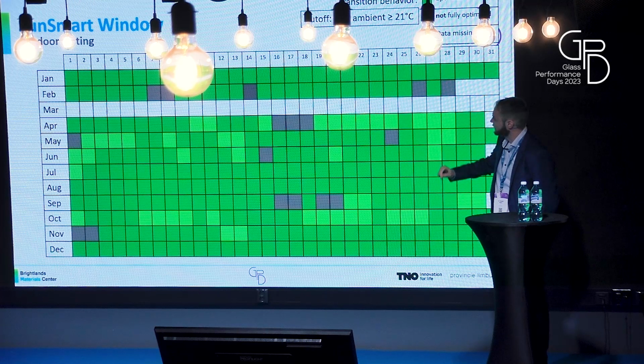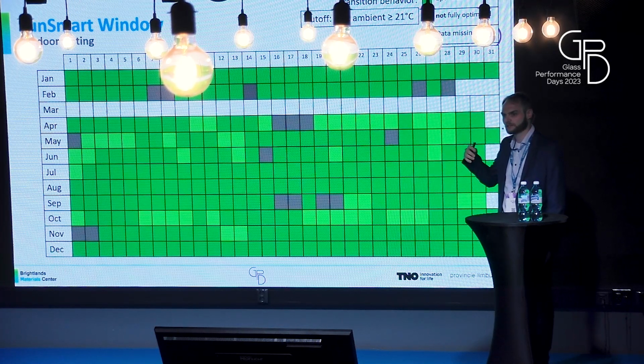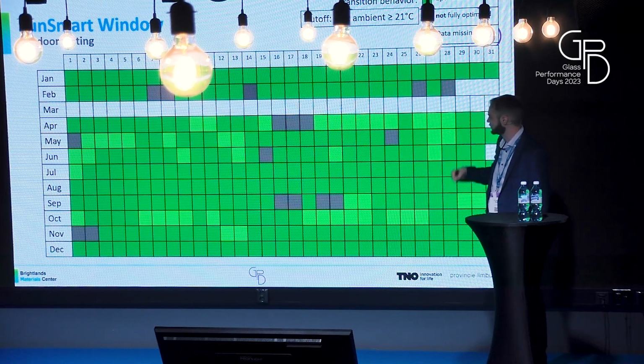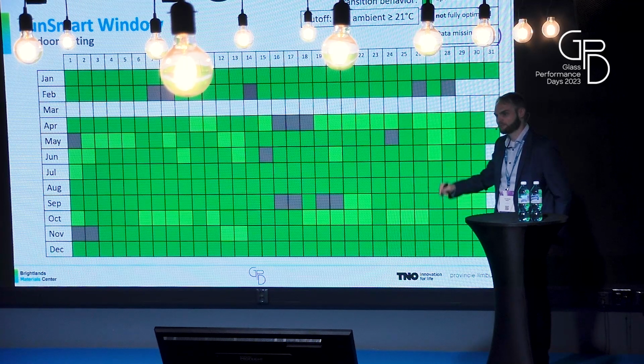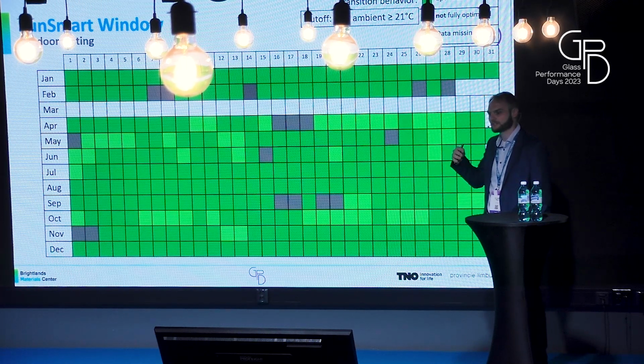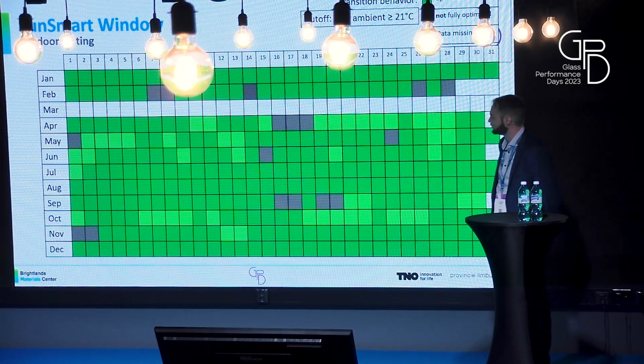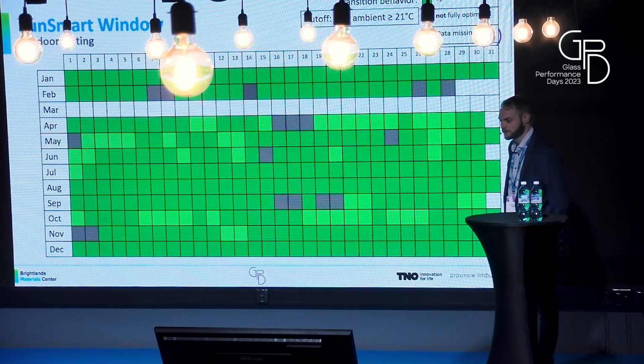So that means we analyze the material: if it switches, and if the ambient temperature went above 21 degrees, then we say, okay, it behaved as we wanted. And if the ambient did not exceed 21 degrees and it did not switch, then we also say it behaved as we wanted. And what you can see here is that especially in summer and winter times, the material already behaves completely as we wanted it to behave.